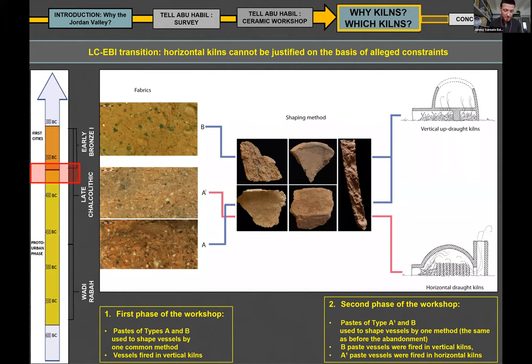And also after the abandonment and the reoccupation of the workshop, there's nothing extraordinary. Of course, A paste disappears after the abandonment, but it is replaced by a very similar group of pastes. I call them A1 because it is essentially the same fabric, but with just the addition of grog. We define grog as crushed, powdered ceramics used as inclusions, mixed with clays to produce new pots, and the first appearance of grog in the Southern Levant dates back to the very beginning of the Early Bronze Age I. So the appearance of grog after the abandonment of the workshop at Tell Abu Habil is quite normal. Moreover, after the abandonment and the reoccupation of the workshop, we still have B paste exactly the same as before the abandonment. Therefore, the continuity is quite strong.